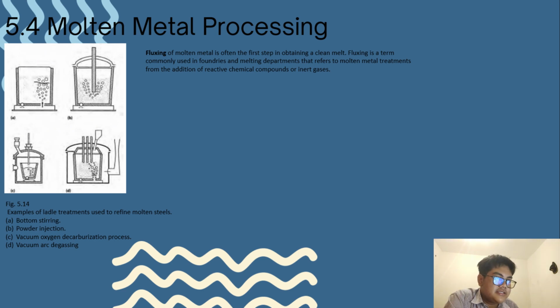As noted, ladle treatments may follow furnace melting, and as we can see in figure 5.14, examples of ladle treatment used to refine molten steels. We get four pictures here: A, bottom stirring; B, powder injection; C, vacuum oxygen decarburization process; and D, vacuum arc degassing. When a primary furnace is emptied into a tapping ladle, the steel can be transferred into other ladles, furnaces, or vessels for treatment. With ladle treatment, steel with a sulfur as low as 0.002% can be produced that is essentially free of oxide or sulfide inclusions.